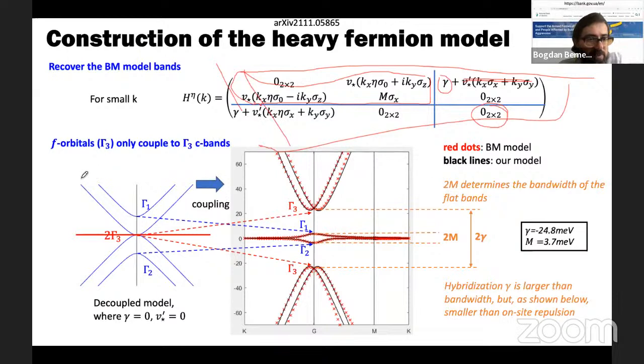So now this blue is the double vortex AB untwisted bilayer. This red is the heavy fermion. You couple them, and what you can see is that this difference between the gamma 1, gamma 2 representations, which is just this mass term, becomes the bandwidth of the Bistritzer-MacDonald model, and the coupling between the gamma 3 representation, between the heavy fermions, this red, and the blue, just becomes basically the gap of the Bistritzer-MacDonald model between the flattish bands and the next bands. So this is the largest term in the system. This gap is the smallest term.